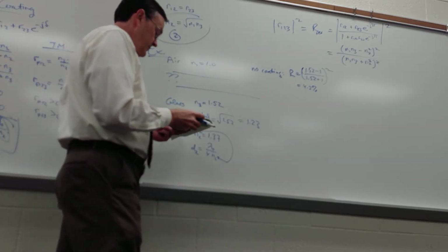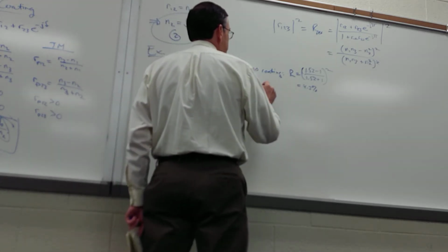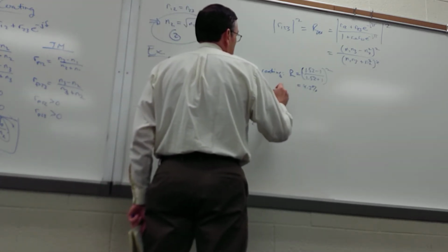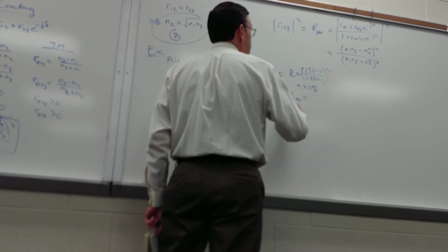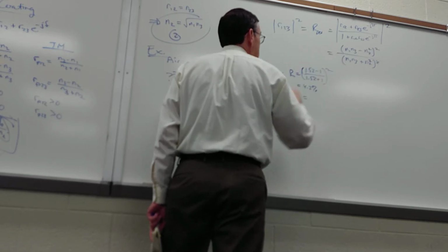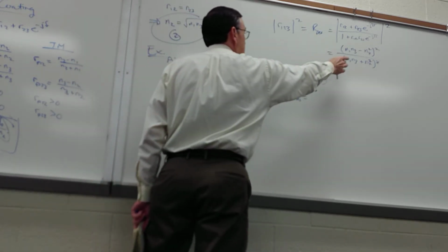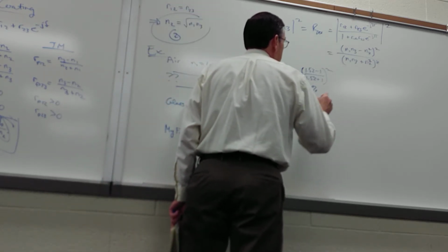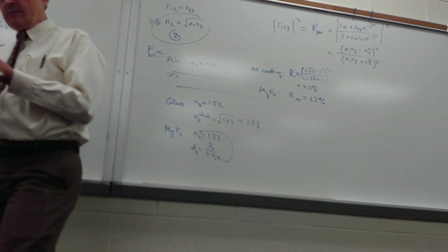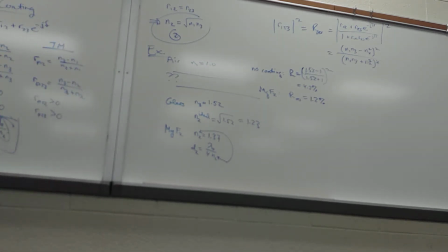If we use the mag fluoride, the reflectance, and I'm just going to subscript it residual because we've designed it at a quarter wave, and we know this is what we end up with. Turns out it's 1.2%. So we got about a factor of 3 reduction in the reflectance by going with the mag fluoride coating over no coating. Is that what they put on glasses?